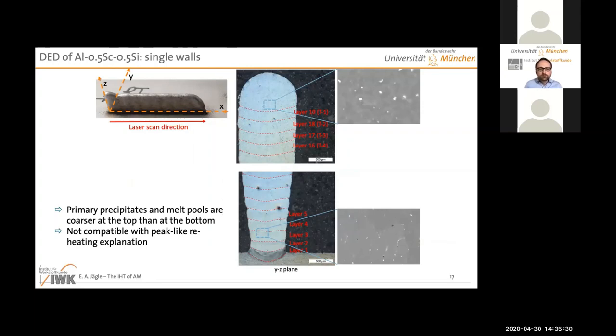One line in one direction per layer. And immediately you see that we have not only this peak-like reheating. Clearly we have a larger melt pool at the top. We have larger primary precipitates. That's in these very high scandium alloys. You can almost never completely suppress the primary precipitation, and probably you don't even want it because you need the primary ones for grain refinement, at least in LPBF. So they are much coarser at the top than at the bottom. The melt pool is much coarser. So obviously there is something going on more than just peak-like reheating, because peak-like reheating, A, couldn't do that, and B, the top would have basically smaller precipitates than the bottom.